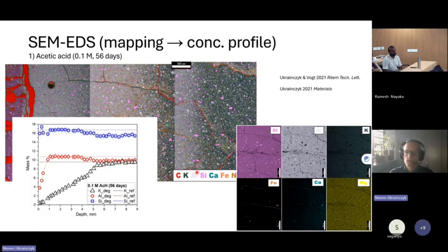But I think it's good to add some calcium inside, some slag, and then you actually have less porosity, more disconnected pores. The problem of geopolymer is that the pores are very small, which is good, but they are connected, and the drying shrinkage and cracking is problematic. But if you add calcium, you are basically lowering this very small porosity, the gel pores, and then you have less porosity, so it's good to add some calcium. But then you maybe have setting problems. We work mostly with pure geopolymers, but I think it's better to add some calcium also inside. This is what we are doing now. It will improve the properties for sure.